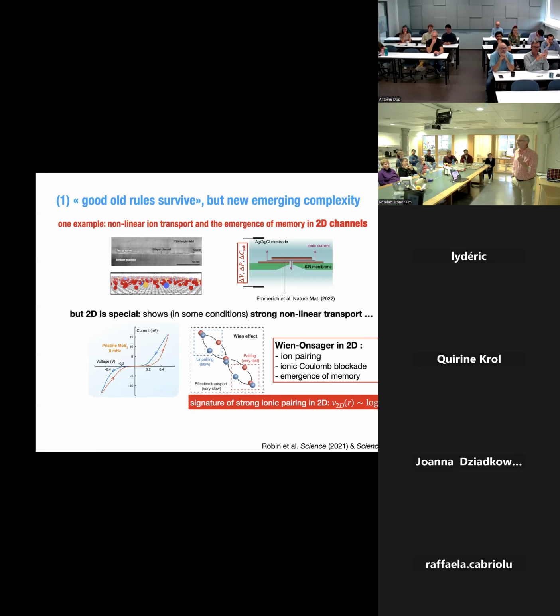But here in 2 dimensions, your system is really something like that. You have a monolayer of water, a monolayer of ions. And when the confinement is insulating, actually you also confine the electrostatic field between the system. And then if you are in 2 dimensions, the electrostatic interaction, Coulomb interaction, is logarithmic, very, very strong. And then, of course, you make pairs, ionic pairs.